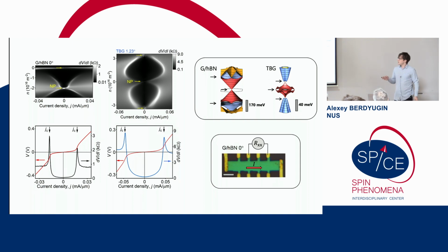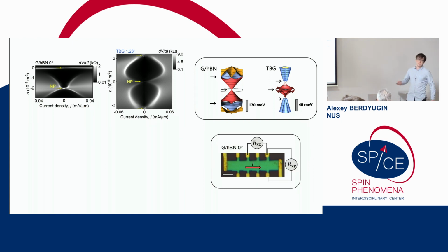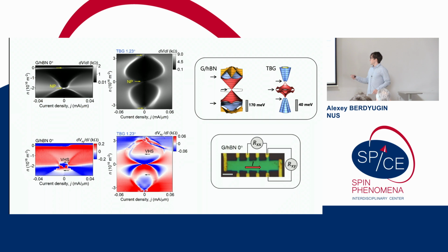To study this effect further, we decided to measure the Hall effect to understand if we might see something interesting there. For this, we simply measure the Hall voltage and measure the IV curve of the Hall effect, basically. And the result you can see here. Here you can see the differential resistivity of the Hall effect, and you see quite a good correlation with our longitudinal resistivity measurements. Every time we reach the transition point in our longitudinal resistivity, the Hall effect tends to change its sign.